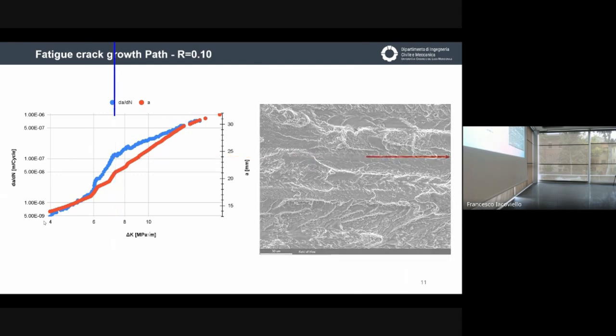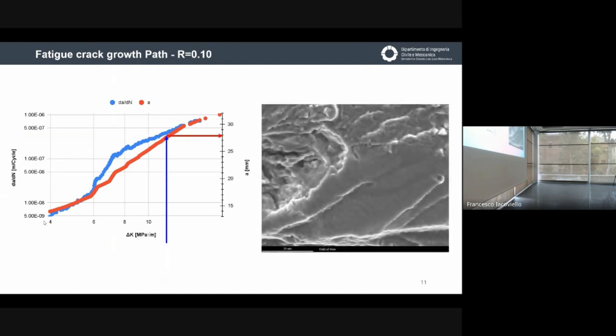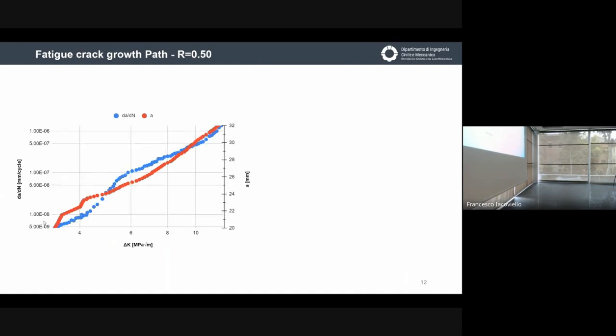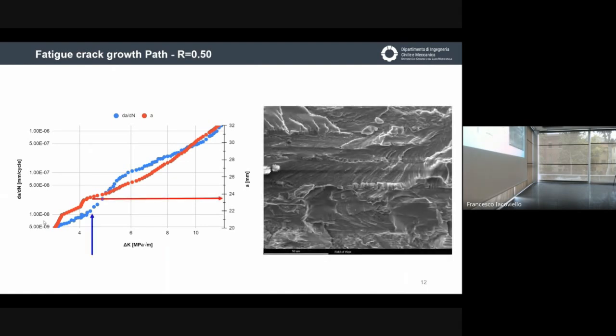In the last stage, the aspect seems to be much more flat, but increasing the magnification, you can see that we have the typical fatigue striations, but at high magnification. So consider the different load ratio. We have the same effect, but the zone characterized by a flat mechanism and the fracture mechanism seems to be much more important.